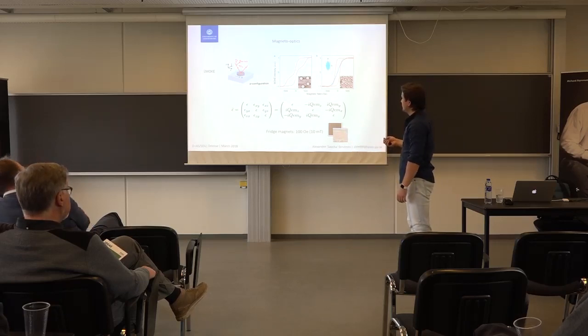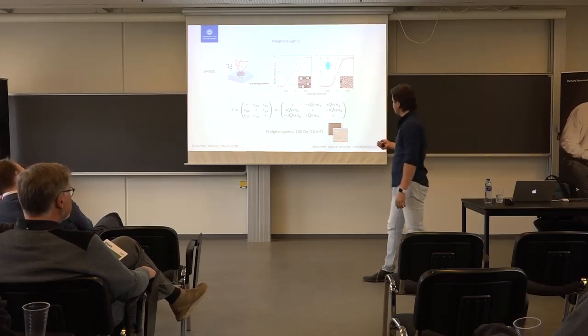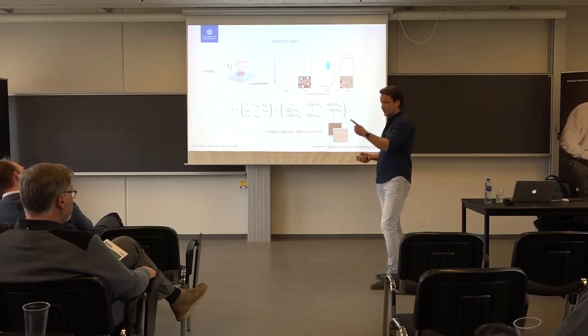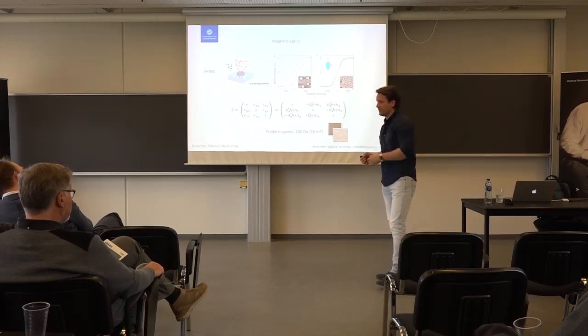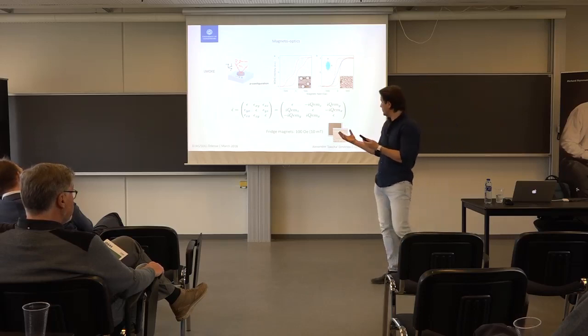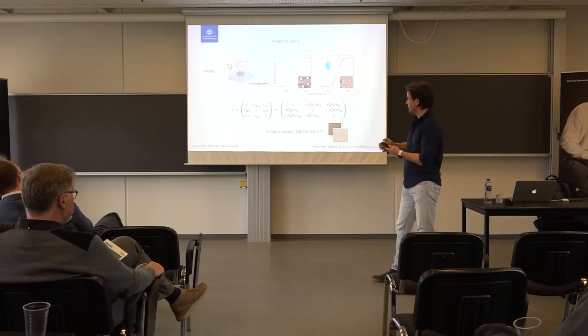But then back to the interpretation of that loop: you can actually see quite a lot of features just by measuring the rotation of polarization. For example, for these disks, you see the narrowing here in the middle, and that signals that your magnetization, originally in plane, starts to curl upwards and form a vortex state. At some point it gets stabilized, but then it decays. You continue applying magnetic field, and it goes back into the in-plane position. So that narrowing signals that.